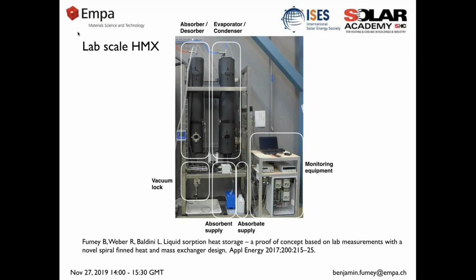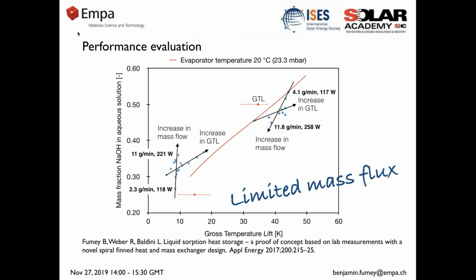On one side, the absorber, desorber, a similar build, the evaporator, condenser, and here are now some of the performance results we reached with our setup, again shown in this gross temperature lift and mass fraction mapping. And the red here now is the equilibrium line at 20 degrees. I show this equilibrium line because these tests were done at a condensing and evaporating temperature of 20 degrees, which I must state, as we saw previously from the realistic temperatures, is of course not quite fitting.